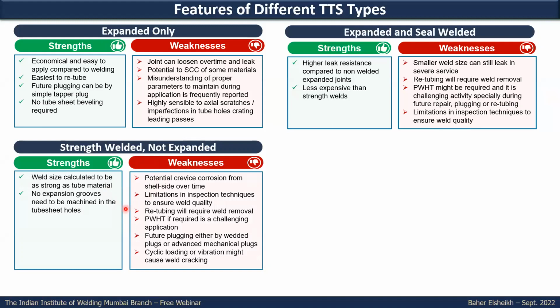Strength welded, but not expanded. You can apply only strength welding without expansion. The weld size is calculated to be strong enough, as we will see in the ASME requirements, and there is no expansion groove needed for such a type of joint. So less machining is required and less work, and there is no expansion, so this step is eliminated. But it is potentially subject to crevice corrosion, because the backside of the weld will have a gap where fluid from the shell side can accumulate and cause crevice corrosion.